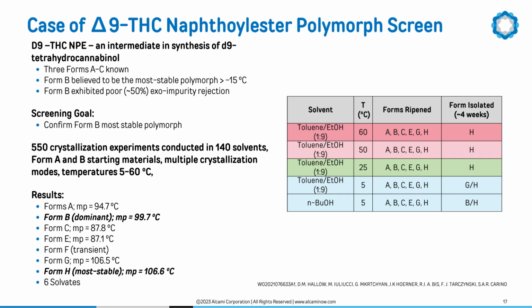Even though form B was the predominant product of the polymorph screening, it was determined via competitive ripenings to be metastable. Its conversion to more stable forms was very slow, taking up to a month of stirring at various conditions. Its slow conversion was probably due to low solubility, potentially present impurities, or slow nucleation and growth of the more stable forms.